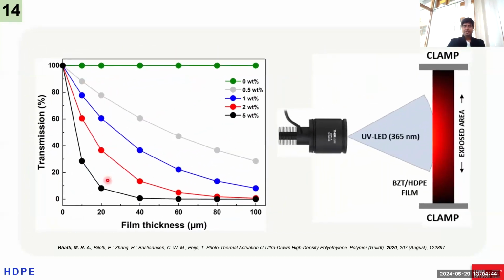But the problem with the higher concentration was that we were unable to illuminate the whole film. With the increase in the concentration of BZT, since the light photons are being absorbed by the BZT, if more BZT is present within the films, there will be more absorption, and technically there will be a dark region behind the film through thickness. That means the light does not reach that point because of the high film thickness, or maybe the higher concentration of BZT restricts the light from getting to the later end of the film. That means there is a thermal gradient generated within the films.